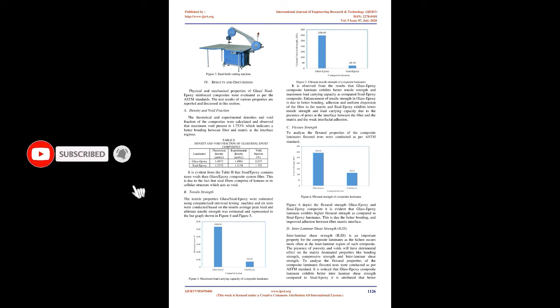In order to remove the excess mixture, a perforated sheet and breather sheet are placed onto the surface of the glass fiber. Vacuum pressure is applied to the composite system for about 1 hour or 30 minutes in order to remove the air bubbles and excess resin in between the layers. Curing of the composite system is carried out for an hour at 100°C.